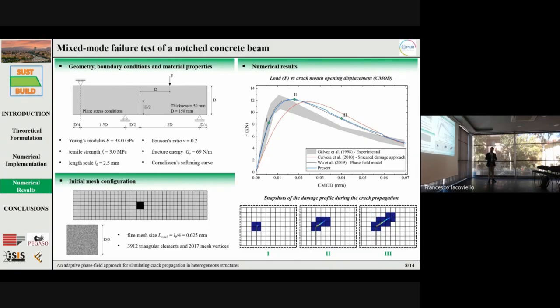The first is a mixed mode failure test of a notched concrete beam having the following material properties, and Cornelissen softening curves are employed to capture the material degradation during the crack propagation. The zone of interest consists of 4 microsubdomains, and the mesh of a single microsubdomain involves 2,017 nodes and 3,912 elements.